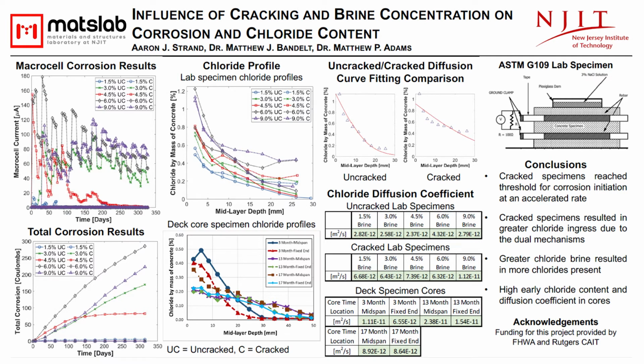These results of testing corrosion of embedded reinforcement at various brine concentrations and cracking conditions show that the presence of a crack and the ponding brine concentrations have an effect on the rate until corrosion can initiate, the measured chloride concentration of the concrete, and the apparent coefficient of diffusion of the system. Overall, the data shows how the presence of a crack within the system will greatly reduce the time until corrosion can initiate when a sufficient brine concentration is present.